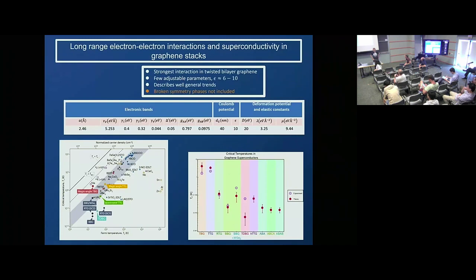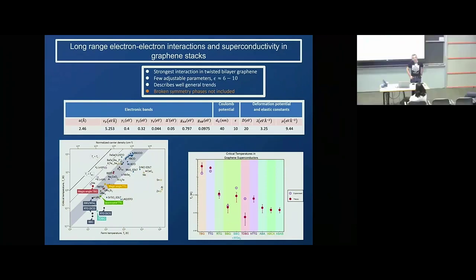That's a good point. I think twisted bilayer graphene at the first magic angle is very unique. You can cook up similarities to twisted bilayer graphene if you couple the two valleys by a substrate like silicon carbide, things like that. But the combination of Umklapp processes and so on, which really helps the superconductivity, I think you only find in twisted bilayer graphene. As I said, you have a double bilayer and it's gone.